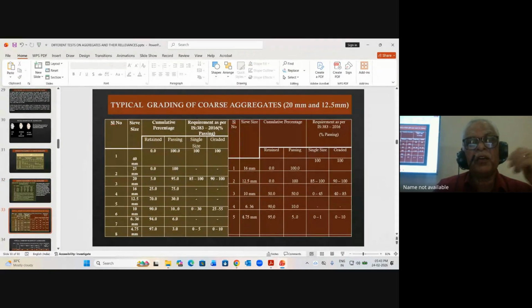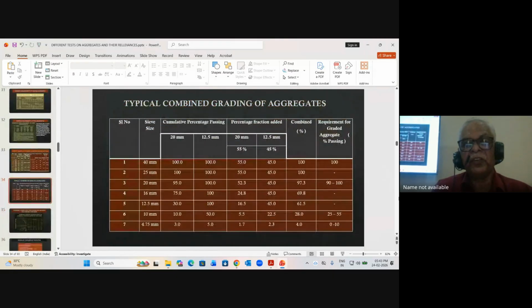This is a typical example, one is 20 mm aggregate, the other is 12.5 mm aggregate. Just to give an example, I will not go very into this because you're doing it almost every day. So these are combined against typical 20 mm, 25... 55% of 20 mm passing through I consider.